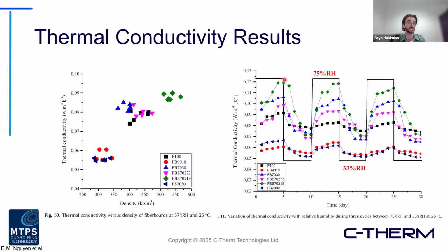With insulation, saturating or getting it wet, or putting it in a higher humidity environment, is oftentimes quite detrimental to its insulative performance. Typically higher humidity, higher saturation will have a higher effective thermal conductivity than the lower end. There are some materials that are more prone to this than others, but they did a really nice investigation here by cycling the humidity condition. This was a 30-day experiment looking at the cycling performance of some of their samples. Ultimately, it's a really nice example of how folks are taking the methods here and looking at some of these peripheral variables, like compression and humidity, and how they impact the overall performance of their materials.